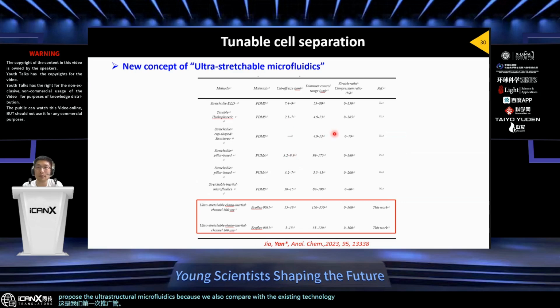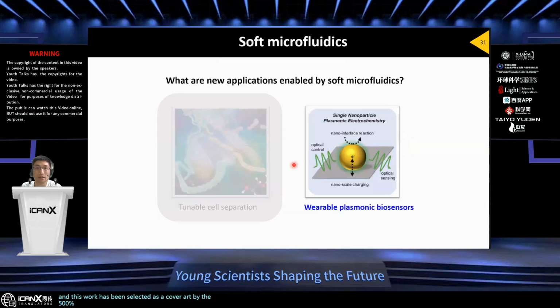Most of them use the PDMS. For the PDMS devices, the stretch ratio is about 100%, but for the ultra-stretchable microfluidics, the stretch ratio can reach up to 500%. And this work has been selected as a cover art by the Analytical Chemistry. The next application is the wearable plasmonic biosensors.